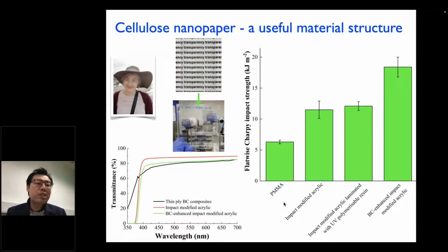We can also throw this nanocellulose nanopaper into a transparent resin. You can make everything ultimately transparent and use this as reinforcement for bulletproof glass. In fact, adding just a small amount of cellulose, you can push everything up by 60% in terms of impact strength compared to a gold standard impact modified acrylic. Now, that's not so much about sustainable materials per se, but making transparent armor lighter reduces fuel consumption. And from that aspect, it is actually more sustainable from a transportation point of view.